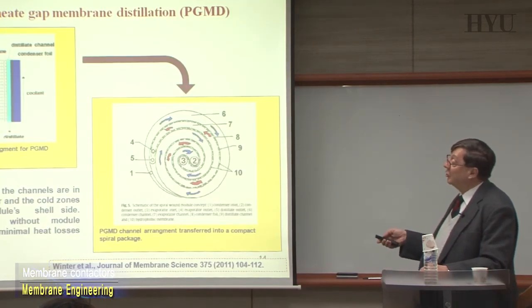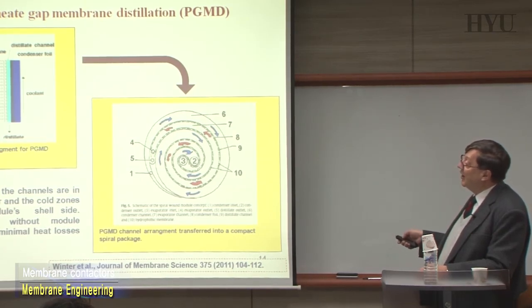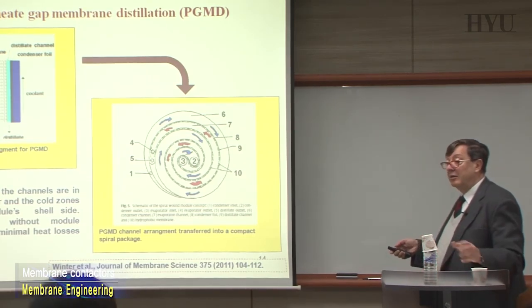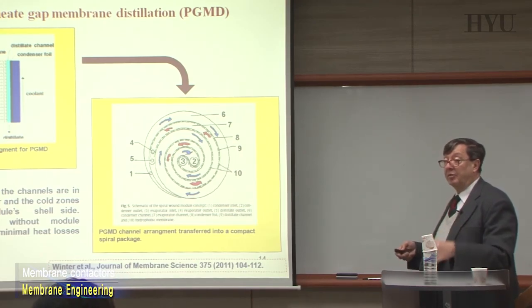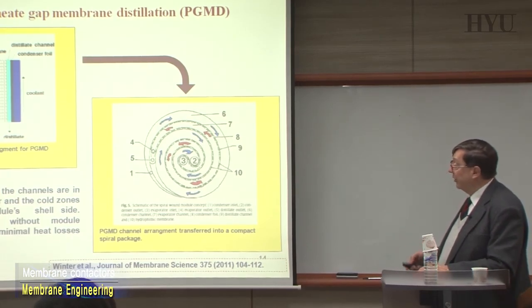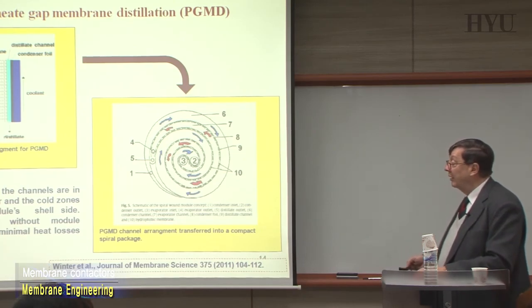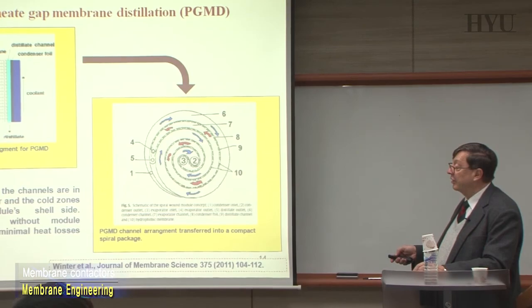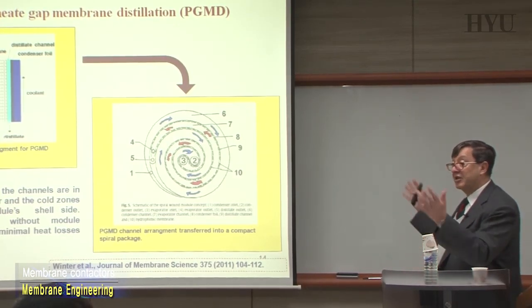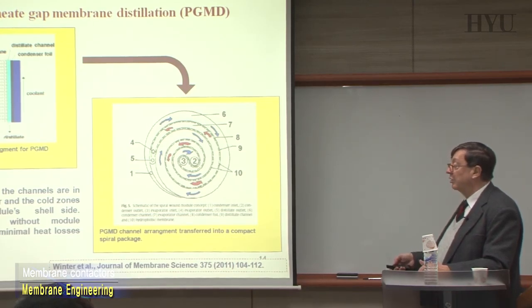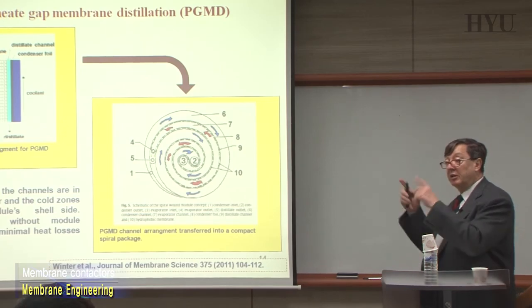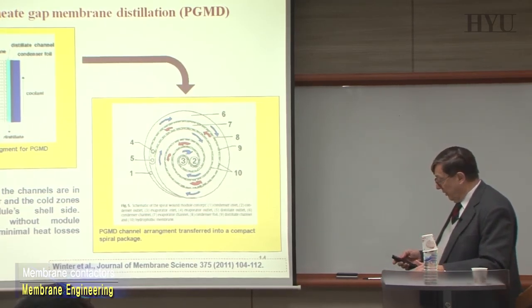That's the way in which this kind of concept can be realized in a spiral wound system, in which you introduce this condenser foil where you condense inside the module the water that is going through. That is a typical example of how you can realize a spiral wound system with a different configuration compared to the traditional one, in which you have the hot zone in the center of the module and the cold zone on the external part of the module, so you reduce as much as possible the dispersion of the heat in the environment, basically. However, it is an example of what can be done, but it really is not yet realized on large scale.